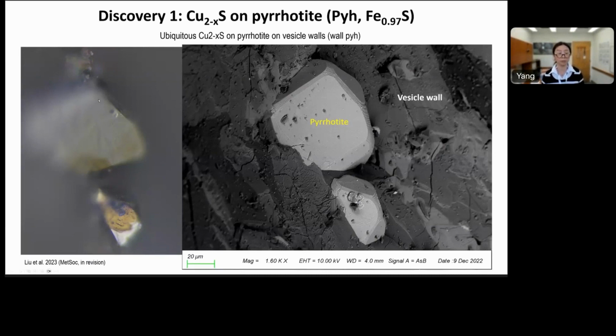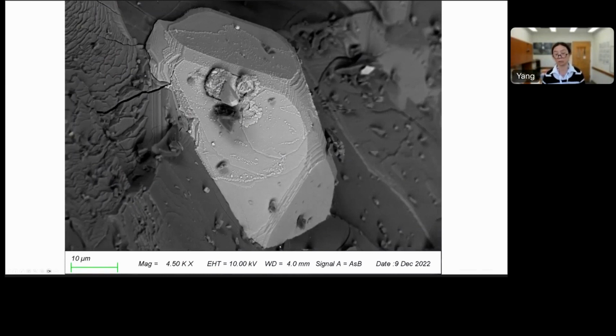So here is one example. This is an optical image of 2 sulfide grains sitting on the vesicle wall. So now you're looking down the vesicle at the vesicle wall, seeing the pyrrhotite grains, euhedral large grains sitting on the vesicle wall. Okay, zoom in. This is the bottom grain, and you see those copper sulfide coatings. There are multiple coatings. There is 1, 2, 3 over here, and you also see there are flow lobate. So the coatings seem to be following this pattern, suggesting some kind of flow.